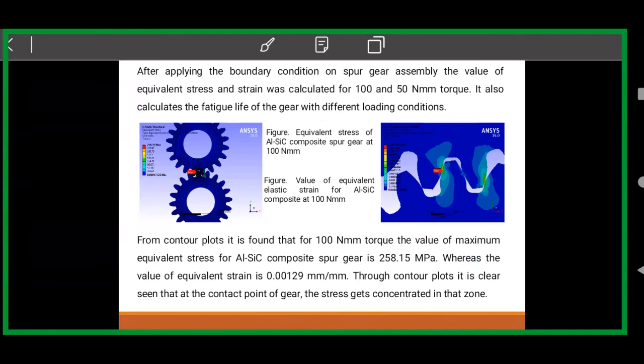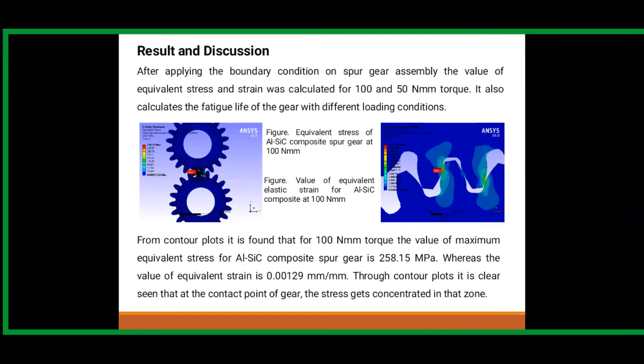From contour plots, it is found that for 100 Newton millimeter torque, the value of maximum equivalent stress for the aluminium SiC composite spur gear is 258.15 MPa, where the value of equivalent strain is 0.00129. Through contour plots, it is clearly seen that at the contact point of the gear, the stress gets concentrated in that zone.